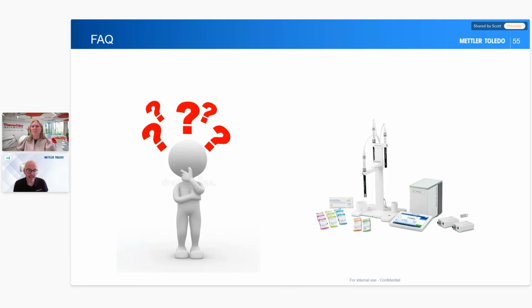Yes. Again, we have a range of different electrodes. I think there's over 90 different Mettler pH electrodes in the range, so you can go and take a look. And one of them is what we call a Solids Pro, or a Solids Pro ISM. This is a puncture electrode, so it's a glass electrode, it's gel filled, and it has a little conical tip, not sharp, for puncturing meat, cheese, solid samples, and semi-solid samples like agar, for example. You could use them in solid samples as long as the solid is a moist sample to take a measurement.